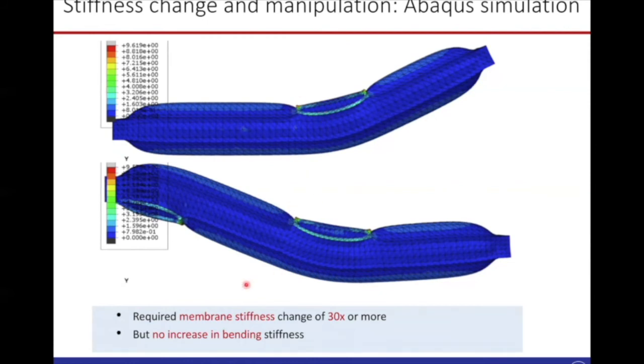Here we need a change in stiffness. So we need to fabricate a fiber which can tune the membrane stiffness at least 30 times or more than that, but without increasing any bending stiffness, because this manipulation itself is a bending process. So if you increase the bending stiffness, then it will be a hindrance for the bending. So we need an increase in membrane stiffness, but no increase in bending stiffness.